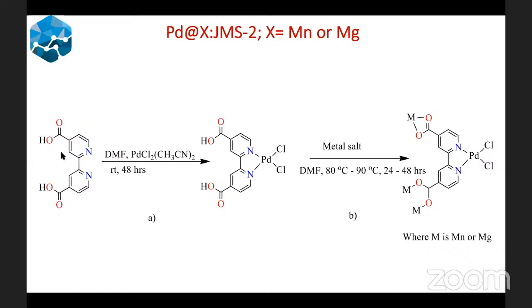In this case, again, we use this dicarboxylic acid bipyridine MOF, and under appropriate conditions, we managed to introduce the palladium catalyst on the ligand, and of course we then used this metalloligand to synthesize a MOF, because already we have the palladium catalyst inside the MOF, and we took magnesium salt or manganese salt.